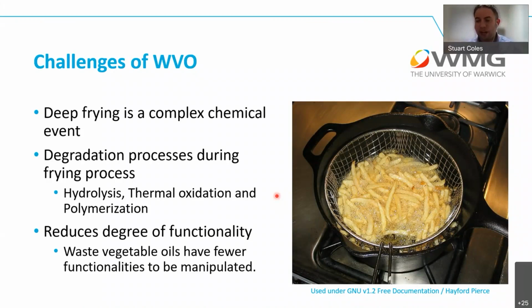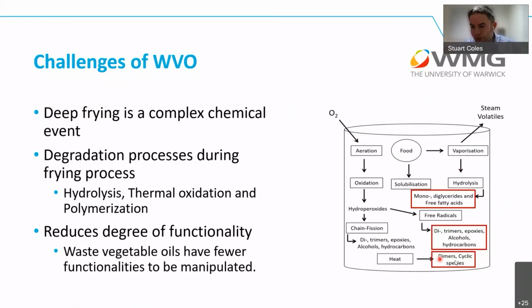And one of our first challenges was to understand how much was that functionality going to be reduced, and whether we could mitigate it in any way, or was it actually going to be a problem in the first place? So we've got a number of processes here, but we're looking at how much do we maintain as triglycerides, how much are we getting as mono- and diglycerides, free fatty acids, are we getting dimers and trimers, epoxies, are we ring opening those with alcohols, and are there any other thermally degraded species that are in there as well?